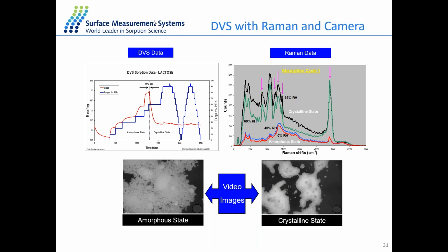Like here, the sample begins as an amorphous sample, and after certain steps like 60% RH, it changes from the amorphous state to the crystalline state. It's happening along with this sorption data. And you see at the second cycle here, it's not showing that kind of change. So it's an irreversible process, and the sample at the end is a crystalline state material.